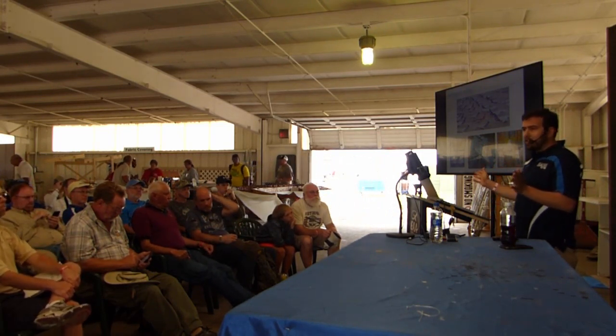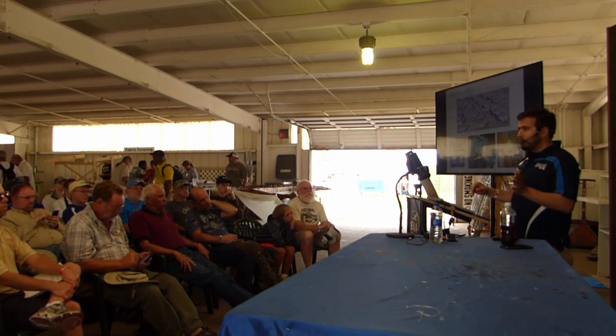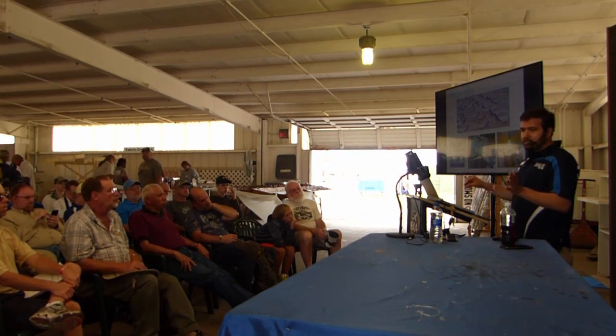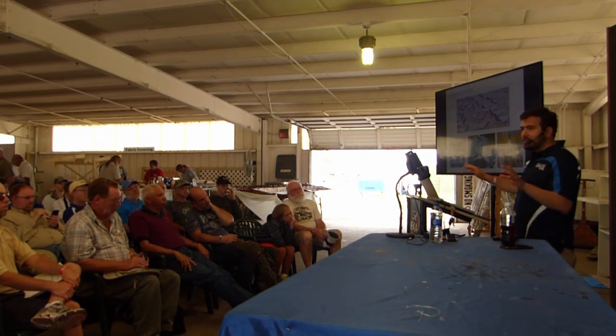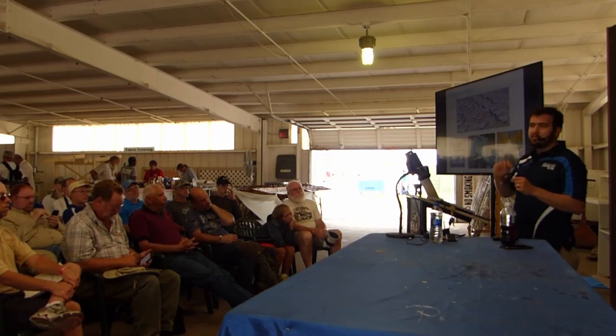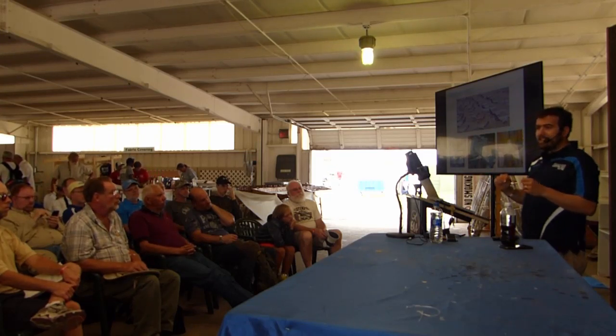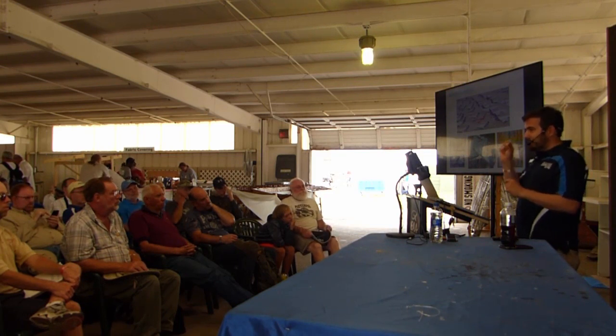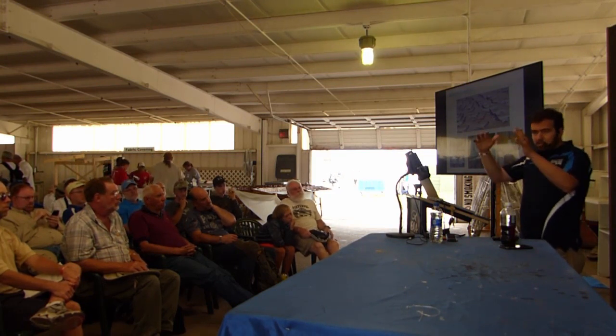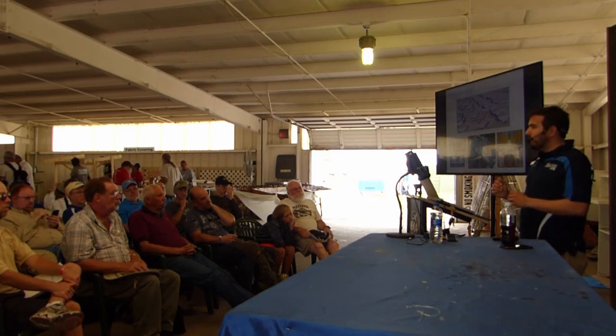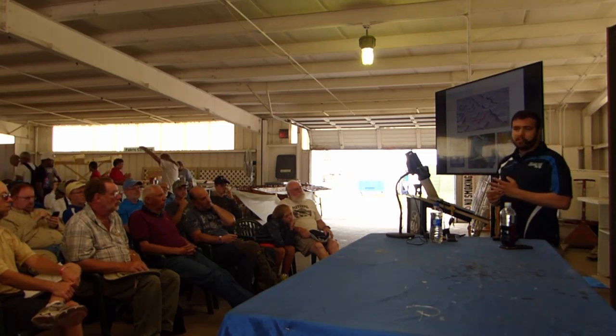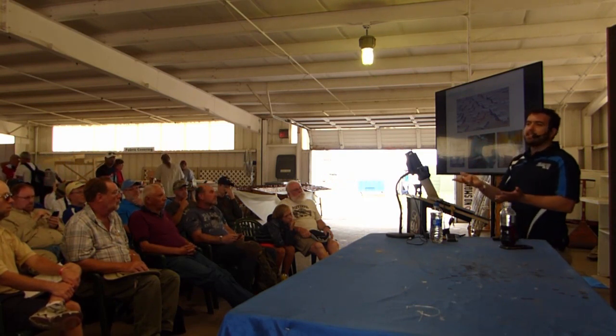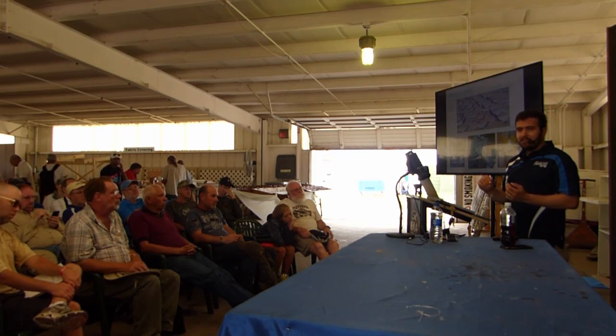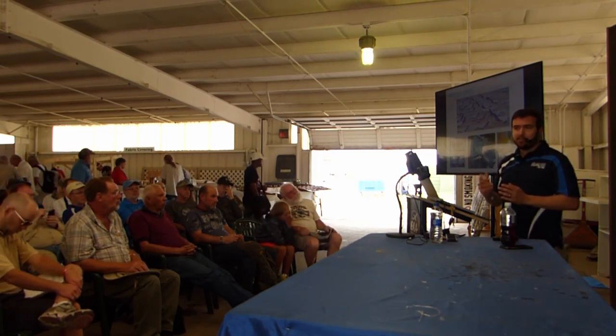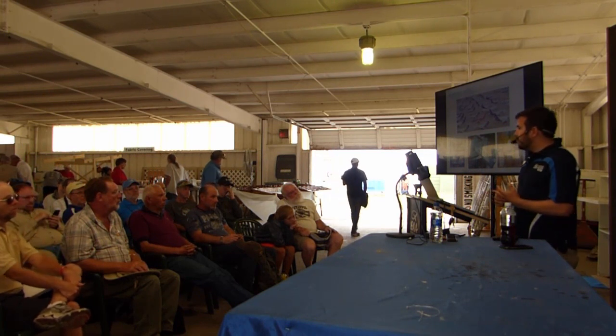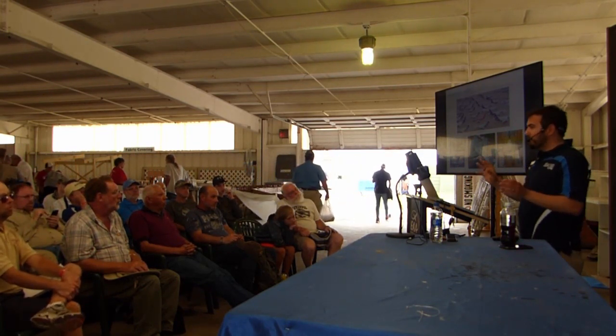But what if over the life of the airplane, instead of one critical detail or one place that sees a lot of stress cracking, you have a whole lot of fastener holes that all see the same stress and they all fatigue crack just a little bit? So instead of having one crack that you can find and detect, you have a whole lot of cracks that are all too small to see, but in aggregate, they drop the strength of your structure below what's safe. So in the late 80s, there was that Aloha accident that you may remember, where the top of a 737 came off, and that's basically what happened. It wasn't one single fatigue crack. It was lots and lots of very tiny fatigue cracks that were too small to catch in service, and that's called widespread fatigue damage. That's the technical term for this phenomenon of lots of little fatigue cracks.